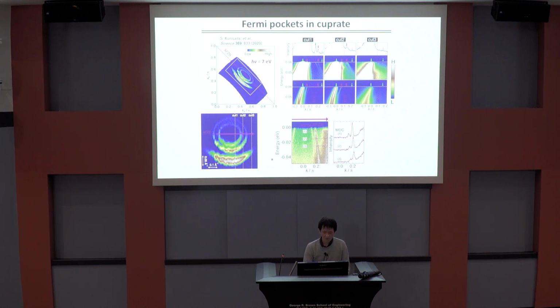We also show the dispersion along the antiferro zone boundary, which clearly shows a very sharp boundary dispersion, which cannot be expected in the case of a Fermi arc. So this is really part of a Fermi pocket, not the Fermi arc.